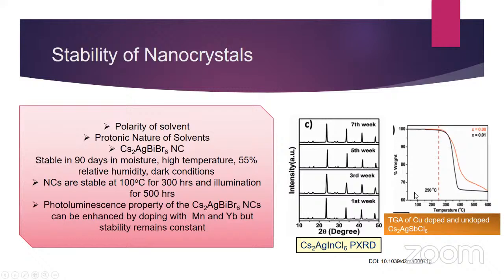In this graph, I have shown you the thermal stability of Cs2AgSbCl6. Here you can see the material is stable up to 250 degrees, and after that the degradation starts. So this is the TGA analysis of the Cs2AgSbCl6 material.